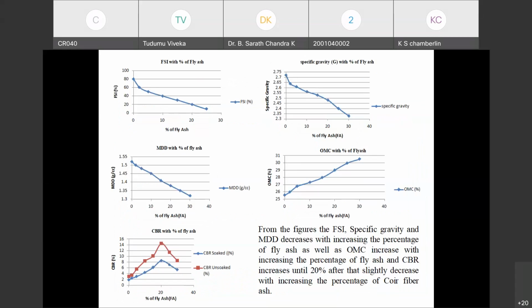And next one is the figures of the FSI, that means free swell index, and specific gravity and maximum dry density decrease with increasing percentage of fly ash, as well as OMC increases with the percentage of fly ash, and CBR increases until 20%. After that, it slightly decreases with increasing percentage of the coir fiber ash.